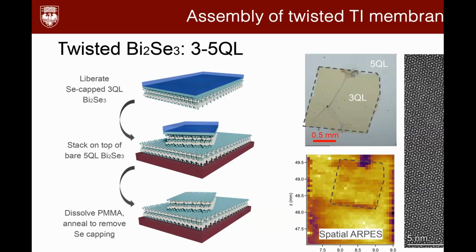Strain, yeah. The bulk lattice parameter is about 3.82 angstrom. STO is 3.9. So roughly tensile strain. But it's not uniaxial, right? It's biaxial, both directions. Right. Okay, last question.